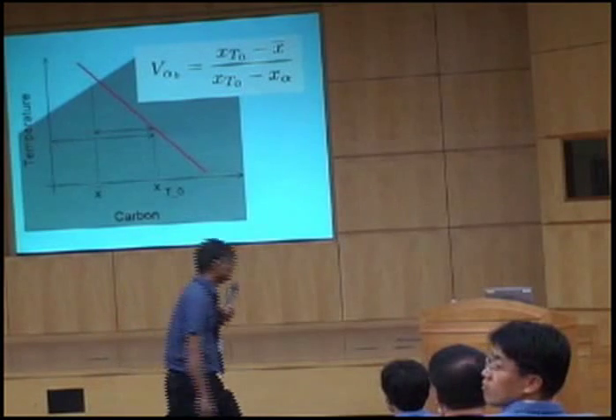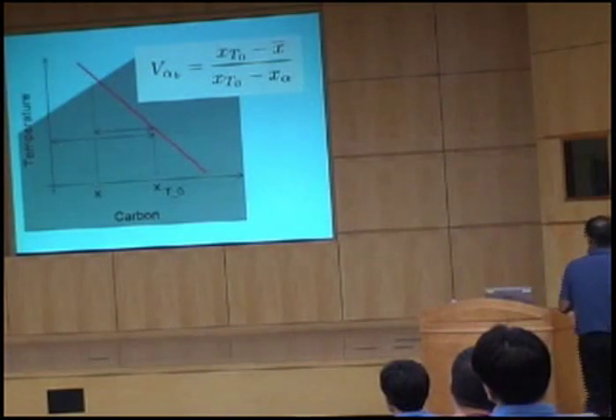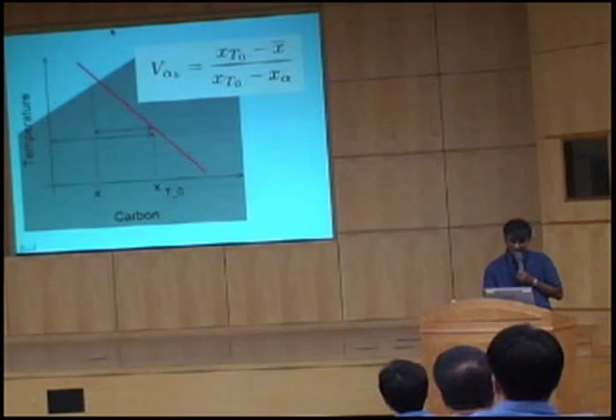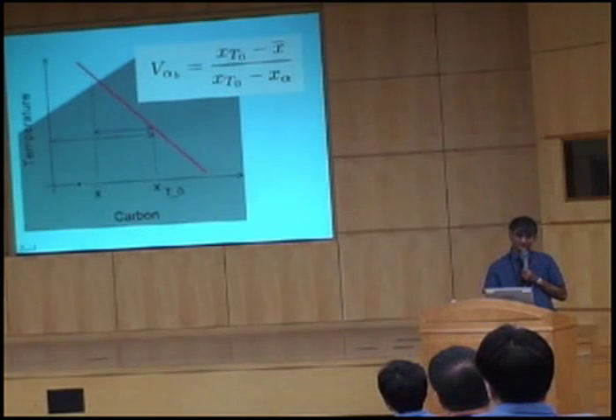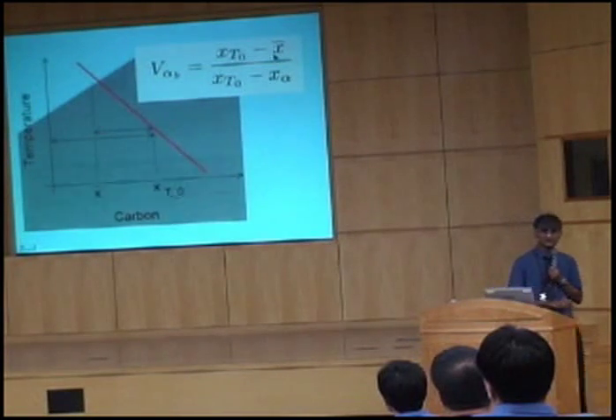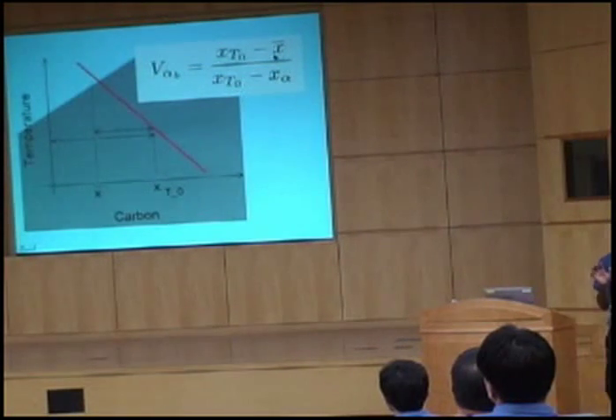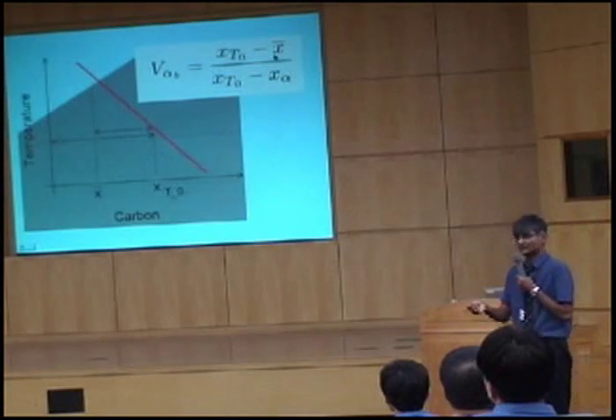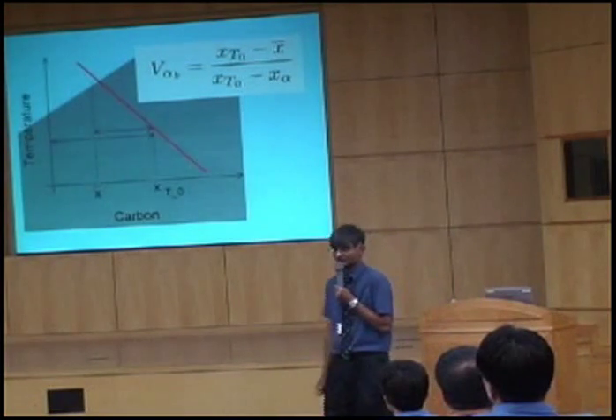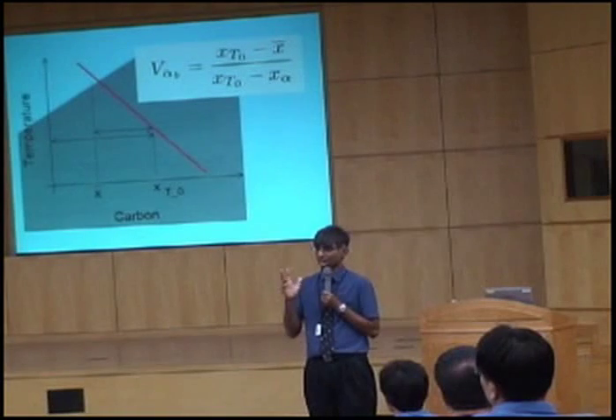Yeah, very good. So one way is very clear, that if I decrease the carbon concentration of my alloy, okay, then the lever rule tells me that I will get more bainitic ferrite, and I will not lose strength because I'm actually producing more bainite, which is the fine structure. Okay, any other methods? There are two.